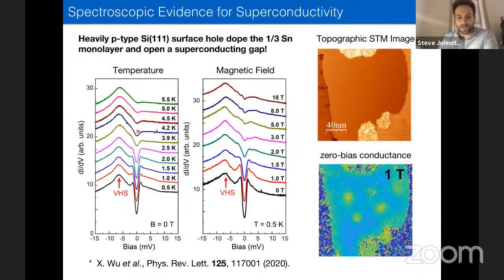But in this new STM, they can go down low enough in temperature that you see really a formation of a nice gap and a sharp coherence peak starting to form at the lowest temperatures. Sure enough, if you apply magnetic fields, now fixing yourself at 0.5 Kelvin and increasing the field, you can suppress this gap. So that's really indicating this is magnetic related, that it's superconductivity related. And then if you do zero bias maps in the superconducting state under a magnetic field, you start to see the vortex lattice forming. The bright spots here correspond to regions of large conductance or large densities of states. So this is indicating a normal state region here, and this is a vortex lattice that you're starting to see form here.